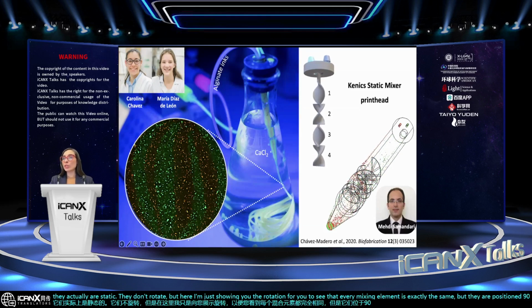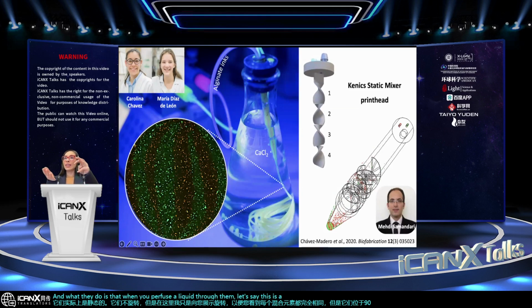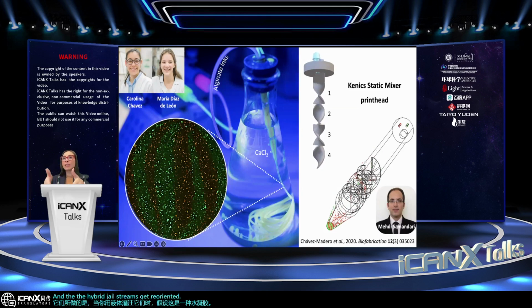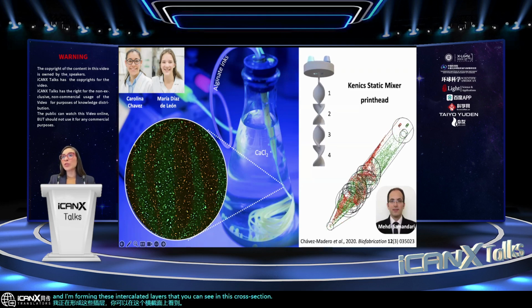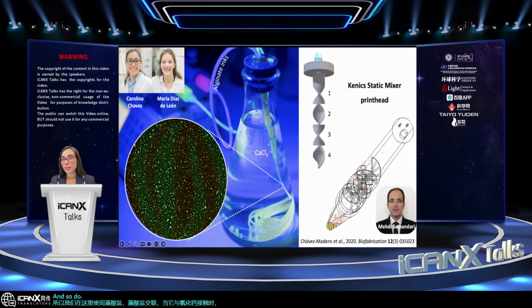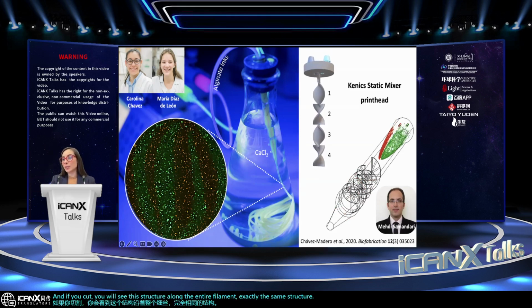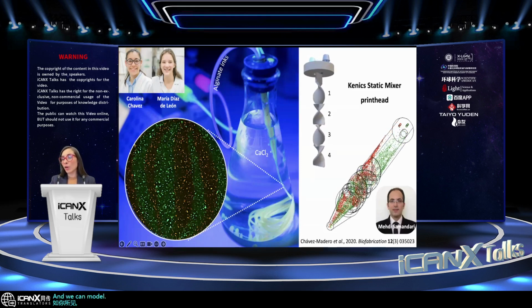And what they do is that when you perfuse a liquid through them, let's say this is a hydrogel, the hydrogel streams get reoriented and then split in every mixing element, forming these intercalated layers that you can see in this cross section. So here we are using alginate. The alginate crosslinks when it comes in contact with calcium chloride, with divalent ions. And so you can extrude meters, literally meters of this hydrogel fiber. And if you cut, you will see this structure along the entire filament, exactly the same structure. And as you can see here, we can model this, we can make computational simulations just to show that the outcome is the same experimentally and computationally.